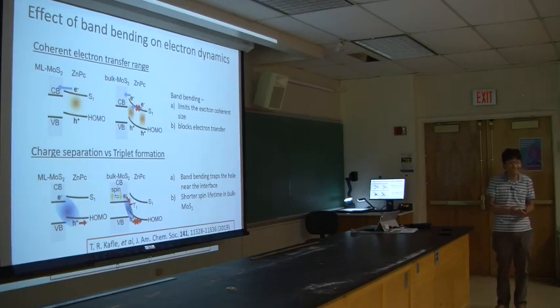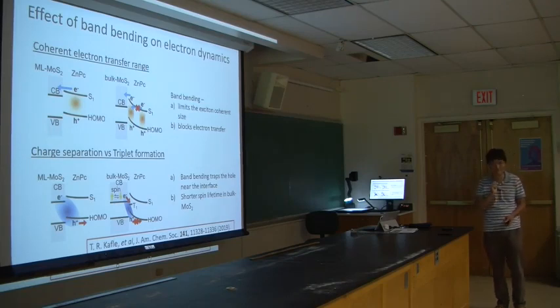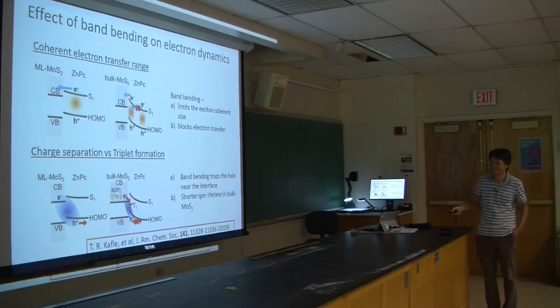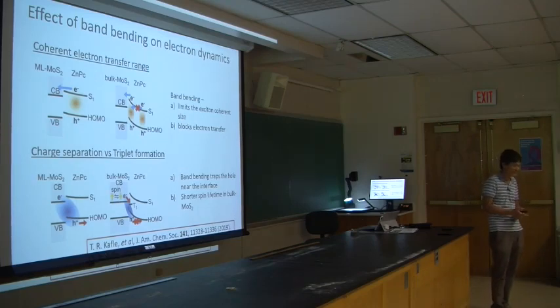And then, more unfortunately, for bulk MoS2, people know that the spin lifetime is shorter, so the spin can flip quite easily in bulk MoS2 compared to monolayer MoS2. So now the hole is stuck and the electron spin can flip. And then the electron can actually go back to the molecule to form this so-called triplet exciton. And another unfortunate combination is that for these organic molecules, the exchange interaction is quite strong.